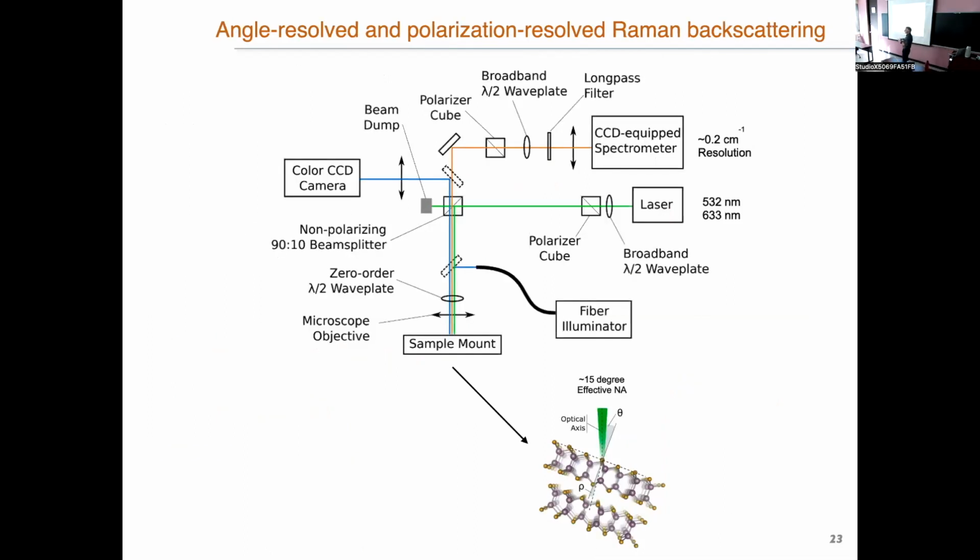The experimental system is very straightforward. We have a sample that's placed like this. We send laser light like this, very narrow in frequency. Then we look at the light that's scattered back, send it to a spectrometer, and analyze the frequency. We subtract the frequency of what's observed from that of the laser, and that gives us the frequency of the polaritons we're looking at.